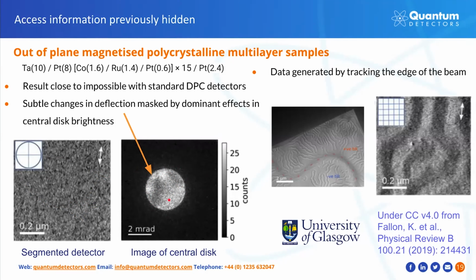But once we utilize a pixelated detector, the MerlinEM detector, we can post-process the data by tracking the edge of the probe, which improves the signal to noise massively. This is shown on the image on the right, where the researchers at the University of Glasgow were able to visualize the domain structure of the specimen and even measure the width of the domain wall here. And just to mention one more time, this is quantitative imaging. So we can characterize exact numbers of the fields within these materials.